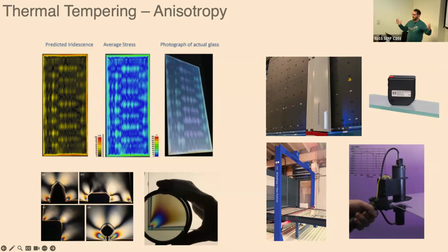But if you imagine cooling down a part, your surfaces and edges are also cooling at the same rate, and you get a ton of stuff going on around edges and corners. This is my comment that edges and corners need a little more love in a rectangular thing that has a lot of edges. Also, if you put a hole in the back glass, when you thermally temper it, your stress profile is going to look bizarre around the hole. It means you have differential stresses, and that tends to be a place where glass is not so happy, with a bunch of different areas bottled up.